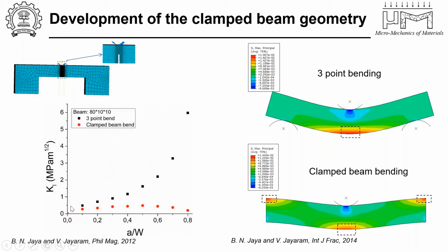Now if you remember one of the slides that I showed early on, the single edge notch bending beam shows a monotonic increase in K1 with increasing a/W. But the clamp beam bend did not seem to do that. It in fact increased and stabilized, and in fact decreased after a particular a/W ratio, which means that for a beam with a crack length of, let's say, a/W of about 0.4 or 0.5, I see a decrease in the driving force for crack growth as the crack increases in length, which means I need to apply a higher load before I continue to break that specimen or continue the crack to grow, even though the material's fracture toughness may be constant across the width of the specimen. So that is what this implies. And we wondered why this was so different.